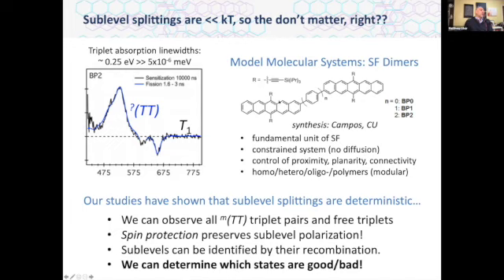Right. We're going to use molecular systems of the type like this, where we take two chromophores and we tether them together. The synthesis is all done by Luis Campos's group. We like these systems because they represent the fundamental unit of singlet fission. It's constrained, there's no diffusion. Luis can control proximity by the type of coupling unit, and where we put the bond, we can control the connectivity. You can make them dimers or trimers or polymers.